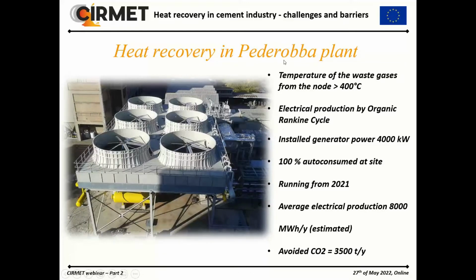And in the other cement plant in Pederobba, the gases are at higher temperature, more than 400 degrees. So we could install a bigger generator of about 4,000 kilowatt. Like in Piacenza, the energy is totally auto-consumed at site, and the system is running since last year. We estimate a production of about 8,000 megawatt hour per year.